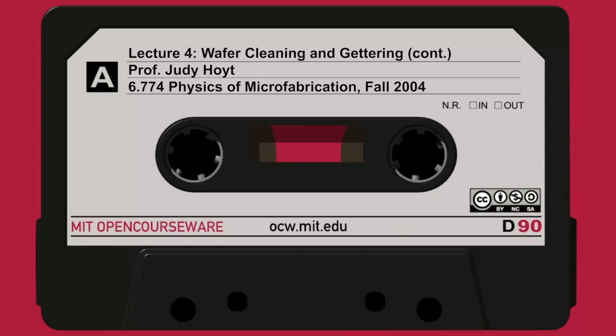So that's extrinsic gettering. So if we go on to slide number 16, we have a schematic of this intrinsic gettering, which is a little more common. Remember that last time we talked, we said that oxygen is present in all Czochralski silicon. It comes from the crucible. There's nothing we can do about it. And it can be introduced in this supersaturated form. That is, oxygen can be dissolved in there because the wafer was cooled at a relatively rapid rate. But there's more oxygen there than the crystal wants to hold at that temperature in equilibrium.